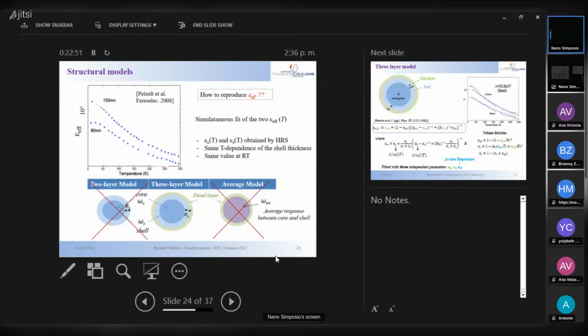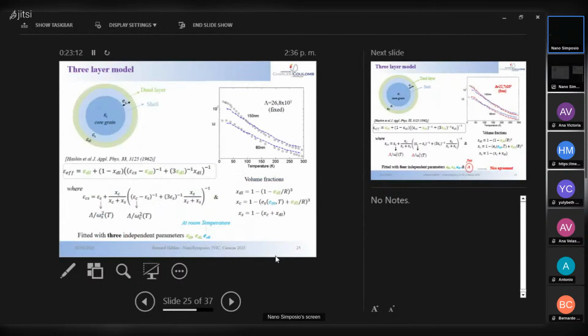And so these 2 models do not work. I will not tell you why, but they don't work. And so to account for this behavior, we need a 3-layer model which involves a core grain, a shell, and a dead layer at the surface. So that's a 3-layer model. And if you do that, the effective permittivity is given by this formula.